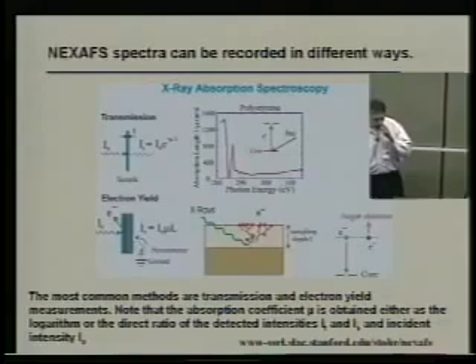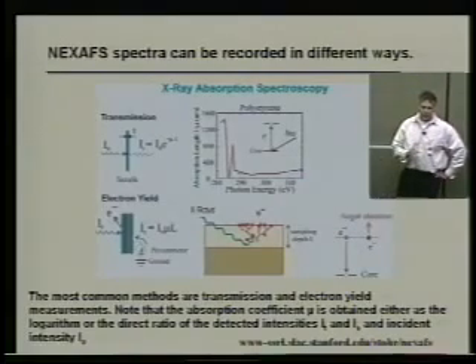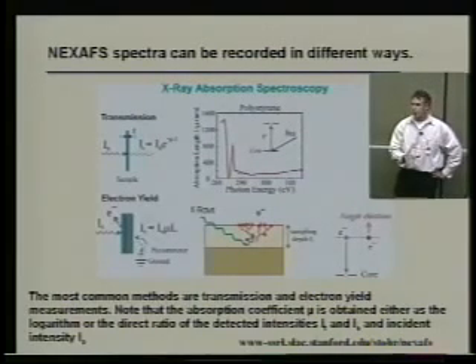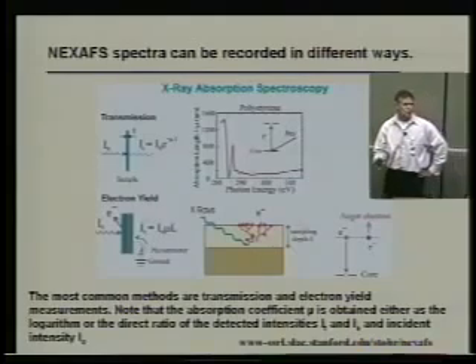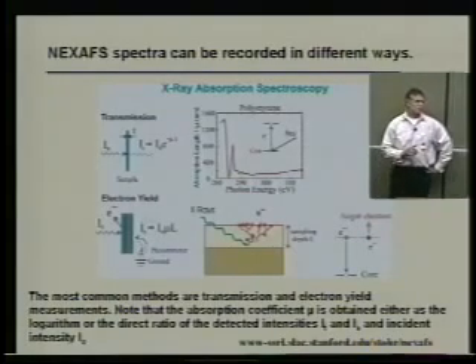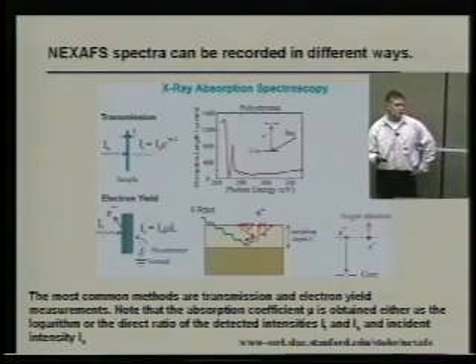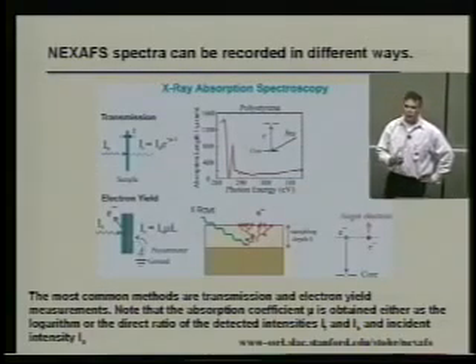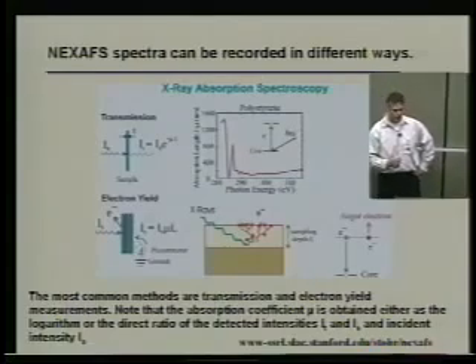Well, the nice thing about doing things in transmission is you actually can get the true absorption coefficient out, because these measurements are a true measure of the absorption coefficient. And it's a fairly bulk-sensitive technique because you're going through the whole sample. The drawback of some of the transmission experiments is you actually need fairly thin samples, depending on what your X-ray energy and what edges you're after, to penetrate through to get reasonable signal.